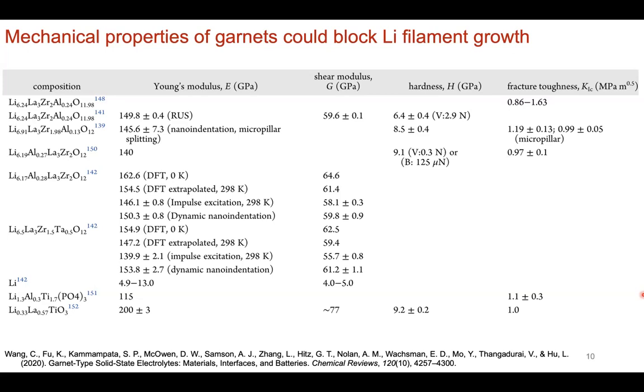Okay. So my reasoning for why I use the term lithium filament growth as opposed to lithium dendrite growth is a purely thermodynamic reason. Dendrite growth, by definition, occurs when you have a solidification process. So if you're going from a molten state or a liquid state to a solid state, that's when your dendrites can grow. So that would be applicable if you were, let's say, using liquid electrolytes, and you're depositing from the liquid lithium ions in the liquid state into a solid form, and that's where the dendrites grow. That's fine. But here, if we're talking about a solid oxide versus lithium, you're having a solid on solid. There is no solidification, right?